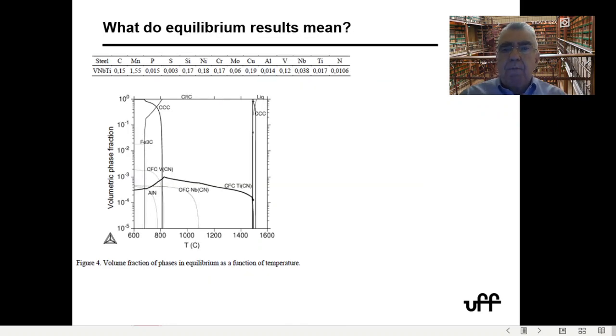Now, if you want to look into more complex steels like this one, which is a vanadium, niobium, titanium steel, and you take into consideration the whole composition, you see that, again, you have a first FCC phase that is a titanium carbonitride, or mostly rich in titanium. Then, at around 1100, you precipitate a niobium carbonitride. Then, at a lower temperature, you precipitate vanadium nitride with carbon in it. And you actually see all these compounds when you do TEM on this steel.